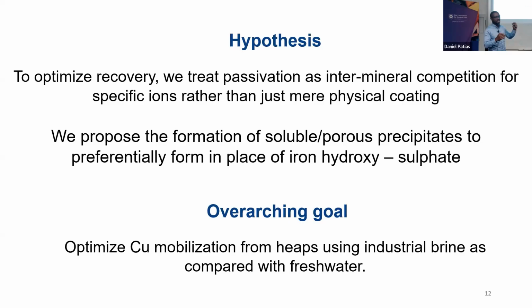In this case, you have chalcopyrite, which is CuFeS2, and it has Fe in it. You're forming jarosite, which also has Fe in it. So it means to form more jarosite, you need Fe. If you have Fe in your system in the form of ferric, which is an oxidant needed to get your copper, then it will be consumed by your jarosite, so you don't get more ferric in solution to mobilize your copper.